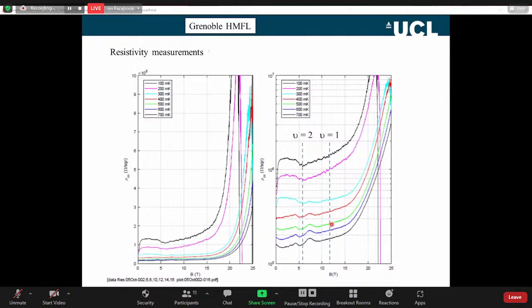Okay. Yeah, so it's still a Shubnikov-de Haas effect, still this magneto-oscillation effect. It's just easier to see here. Interestingly enough, the oscillation is not damped, so the quantum mobility, the quality of the oscillation, is not thermally damped in the way that the transport is temperature dependent.